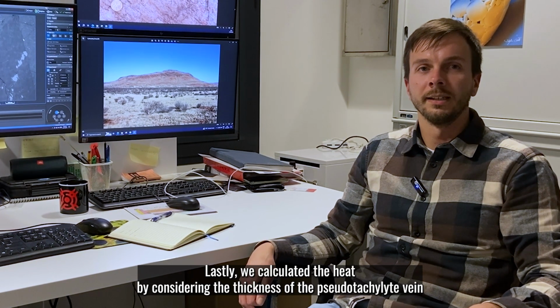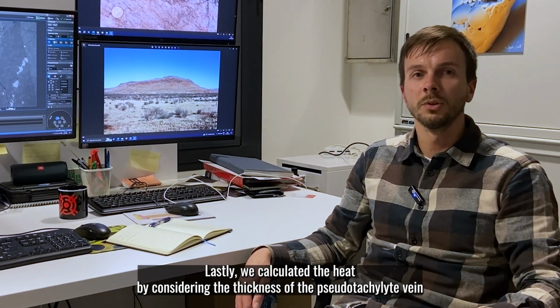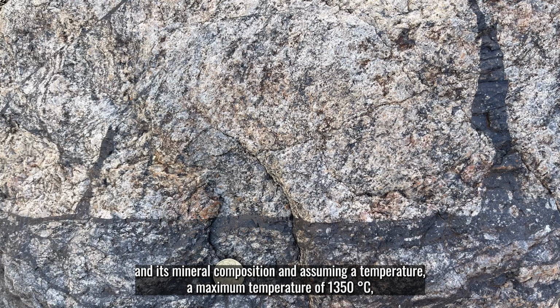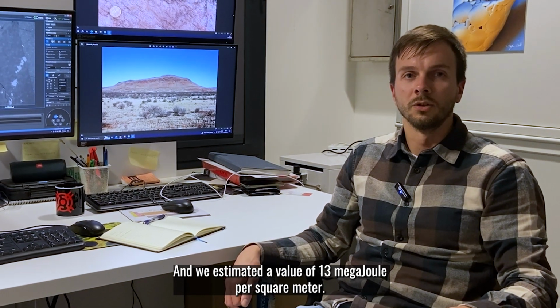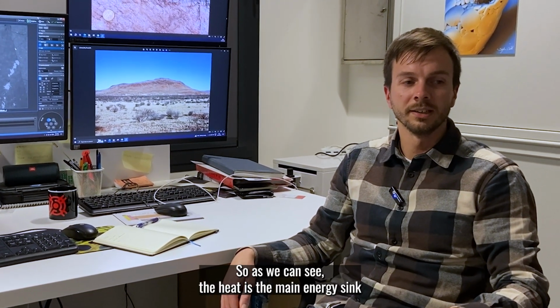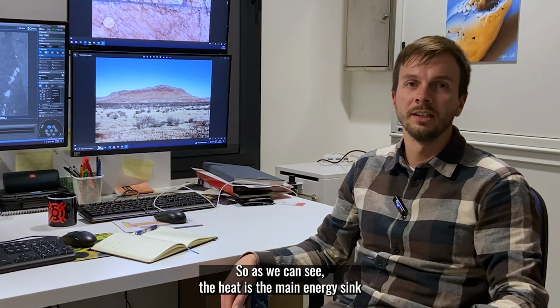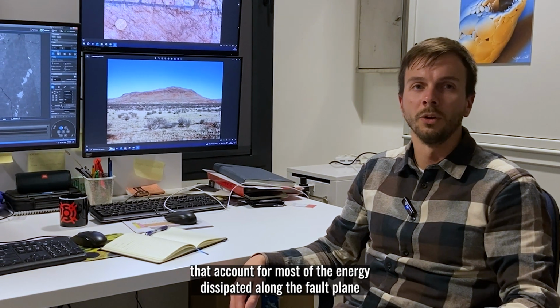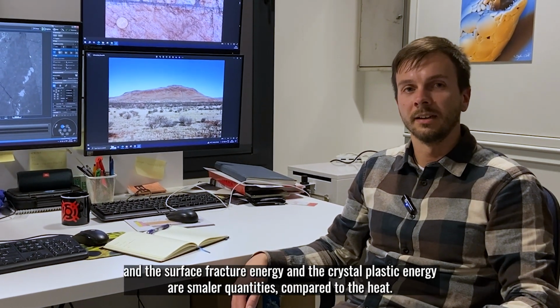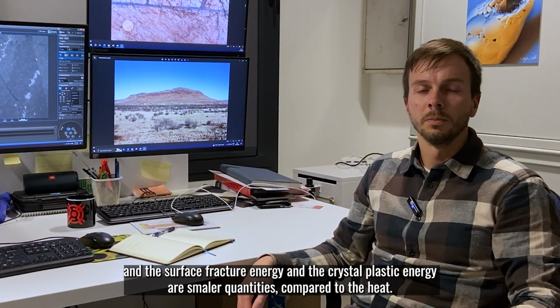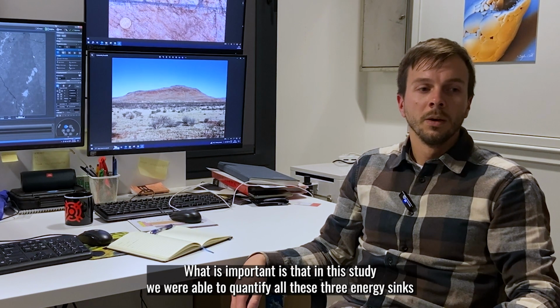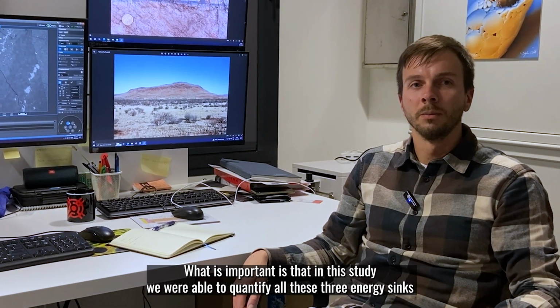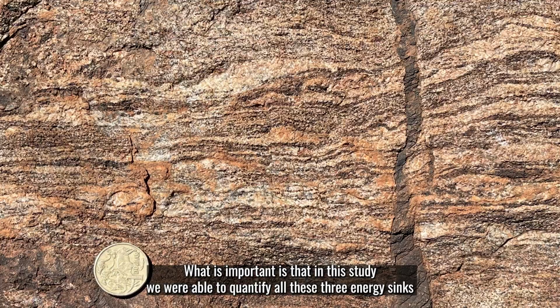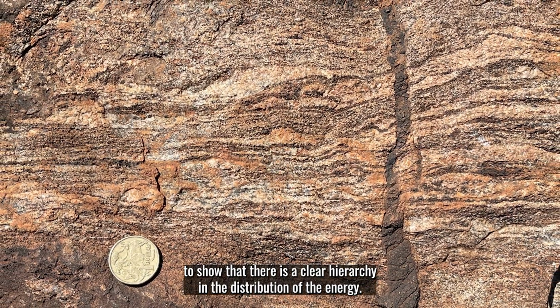And lastly, we calculated the heat by considering the thickness of the pseudotachylyte vein and its mineral composition, and assuming a maximum temperature of 1350 degrees Celsius. And we estimated a value of 13 megajoules per square meter. So as we can see, the heat is the main energy sink that accounts for most of the energy dissipated along the fault plane, and the surface fracture energy and the crystal plastic energy are smaller quantities compared to the heat. What is important is that in this study we were able to quantify all these three energy sinks to show that there is a clear hierarchy in the distribution of the energy.